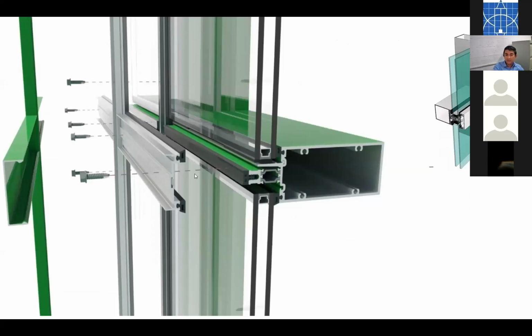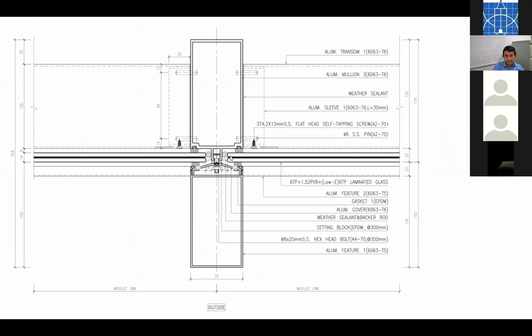Between these, you will have the transom, the mullion, and the EPDM setting block, which would receive the pressure plate, and the EPDM gaskets that go in. But something that you don't see here would be the EPDM setting blocks, the backer rods, and the weather sealants there. Now, if water penetrates here, then the weather sealant and the backer rod are exposed. Then what happens to the laminated glass? From here it starts to get delaminated.